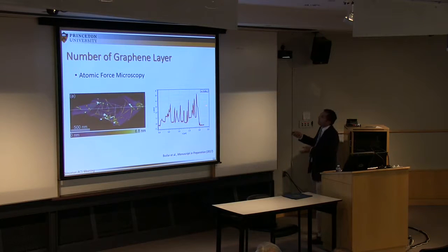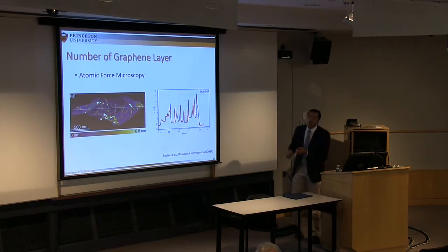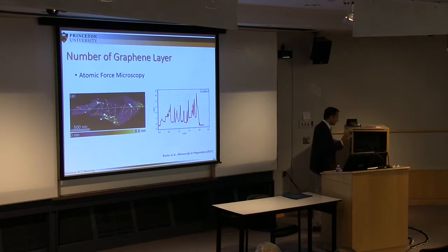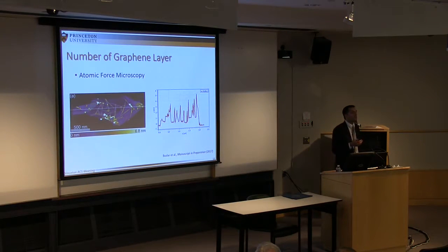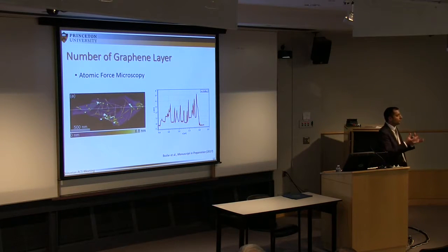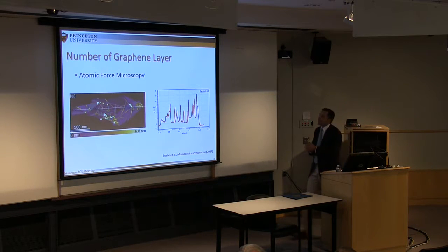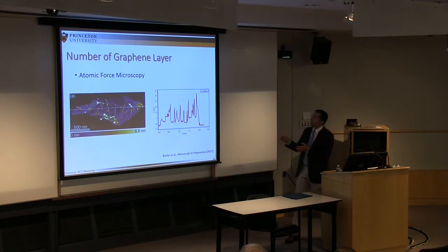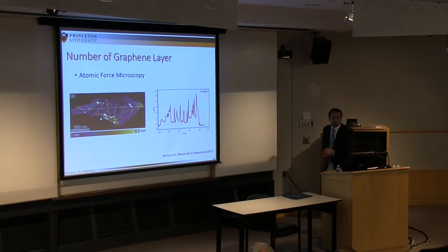And then you can see it goes all the way up to 5 nanometer, and this is coming from this unique property of graphene, this compliance. So it conforms to any surface you put it on. If you were to synthesize it and disperse it in a solvent, for instance, during evaporation and drying, the capillary forces would attract, and the graphene film will bend, basically. That's why you can reach as high as 5 nanometers.